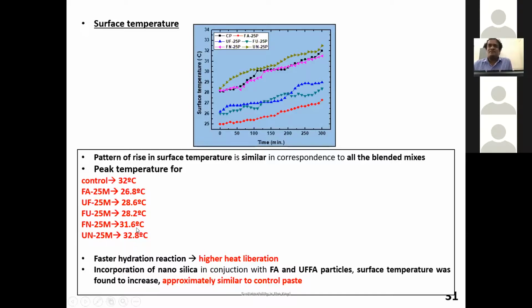But when I'm coming to the nanoparticle mixes, like the blended mixes or the ternary blended mixes, you can see here the temperature is almost close to the control. Now we have to check, and there are some reports also there. With only nanoparticles, the temperature will go up to 40 degrees. The data is not here, but we have checked. The temperature goes to 40 degrees. But when coming to the blend, it is almost similar to the control mix.